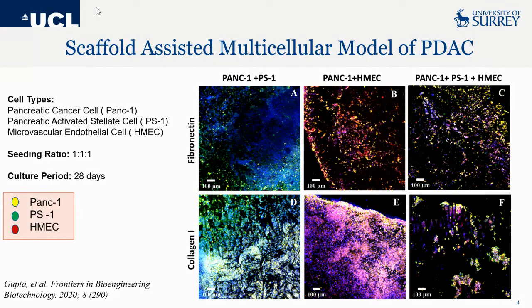cells. As you can see here in the images, we tested out two different protein coatings on our polyurethane scaffolds. On the top panel, you have fibronectin-coated scaffolds, and on the bottom panel, you have collagen 1 scaffolds with the three cells in different permutation combinations. To cut a long story short, when you have a fibronectin-coated scaffold, pancreatic cancer cells survive better in comparison to the stellate cells and endothelial cells. Just to clarify here, the yellow cells are the cancer cells, the red ones are the endothelial cells, and the green ones are the stellate cells.